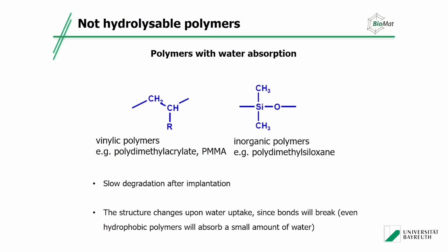So therefore you do not have to replace, if you have this as an Achilles tendon replacement, or at least repair piece, you do not have to replace this because it will not be fully hydrolyzed since hydrolysis is only on the material surface. So it will lose some properties of the original implant, but it will not completely fail. Yeah, that's important to know.